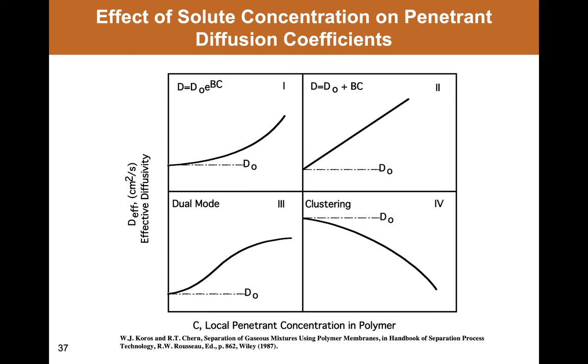The impact of concentration on diffusion coefficients is shown here for a variety of phenomena that are observed in the literature. We've taken and treated diffusion coefficients often so far in the course as if they are constant. However, in many cases, as the penetrant concentration in a polymer changes, the diffusion coefficient will change as well. And this is largely occurring because penetrants can, as they dissolve into polymers, as we've seen earlier, swell polymers, and this can have impacts on the polymer chain motion and therefore transport. And we'll just step through these four regimes very briefly over the next couple slides.